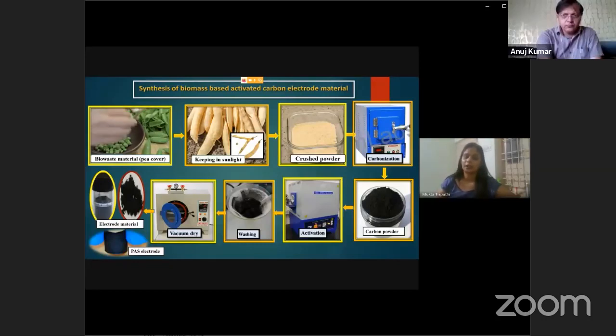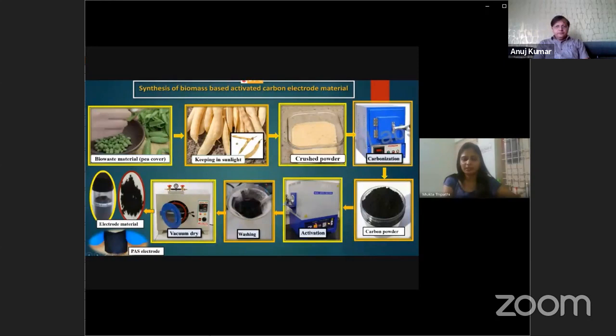Then after we get the powder form, that will be washed with a particular setup, and we use double distilled water. And before that, for the particular activation process, we use the HCl solution at 5 molar concentration, and then we wash it thoroughly with double distilled water, and we get that particular carbon material, and that will be dried using the vacuum oven, maintaining 100 degrees Celsius for 12 hours. We get the electrode material, as you can see in this particular diagram. So that is our electrode material.